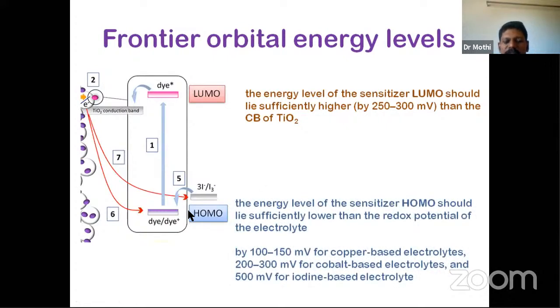Okay, similarly, we can see the HOMO, that is in the bottom energy level, which is the highest occupied molecular orbital energy level. This should lie sufficiently lower than the redox potential of the electrolyte. Here we have iodide, triiodide electrolyte. For different electrolytes, the requirement is different. For example, the most used is iodine based electrolyte. And then nowadays we have cobalt based electrolytes, copper based electrolytes. For different electrolytes, the level needs to be in tune with that of the electrolyte. Okay, so this is about the frontier orbital energy levels.